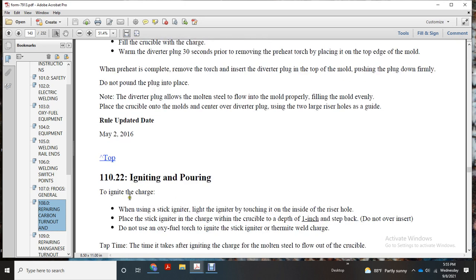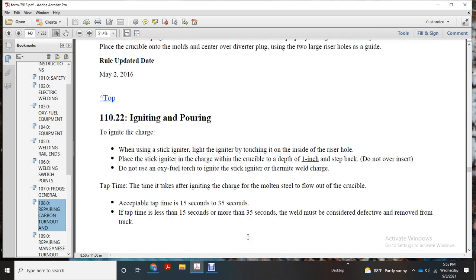Ignition and pouring. To ignite the charge, use the stick igniter. Light the igniter, touching the inside of the riser hole. Place the stick igniter in the charge within the crucible to a depth of 1 inch. Step back, do not over insert. Do not use the Oxy fuel torch to ignite the thermite weld charge. Tap time is the time it takes after igniting the charge for the molten steel to flow out of the crucible. Acceptable tap time is 15 to 35 seconds.